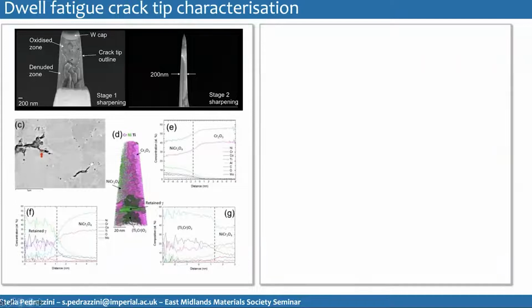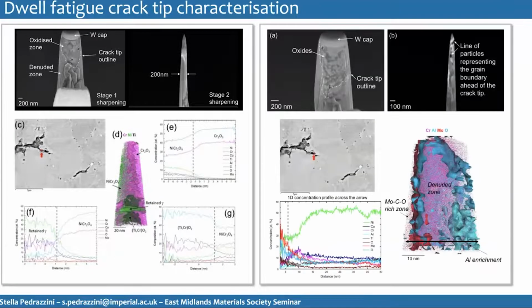And in this case, from here, in the EDX, it looked like maybe a bit of chromia, but it was very hard to tell that there was anything else in there. In the Atom Probe, we can see chromia on one side, nickel chrome spinel on the other side. There was a bit of titanium oxide and a little bit of retained gamma phase in the oxide at the crack tip. So that's already quite interesting, showing that EDX can give you an indicator of what phases are forming where, but it's not really giving you the full picture.